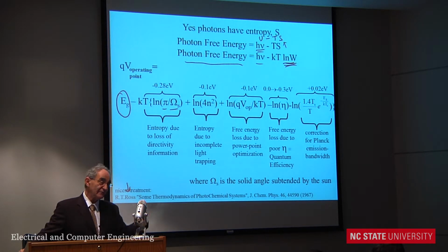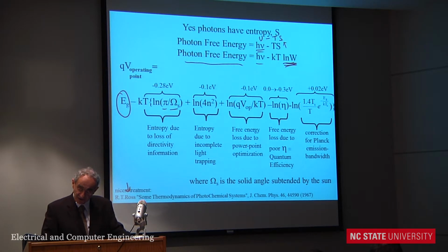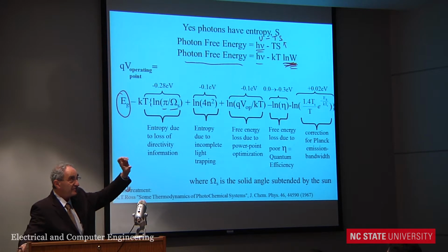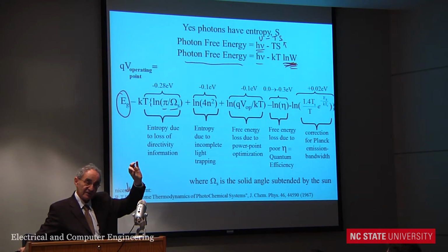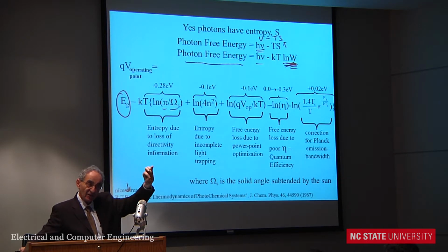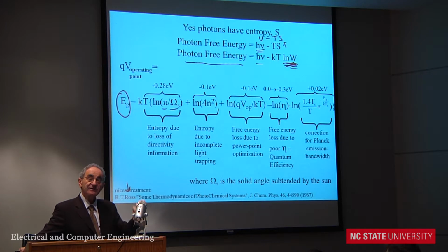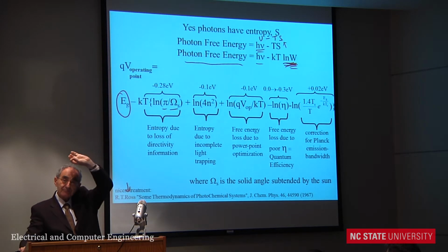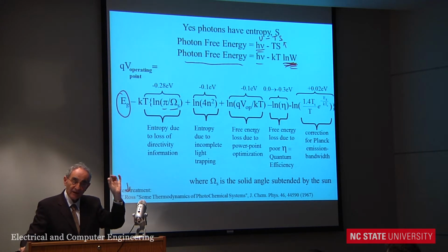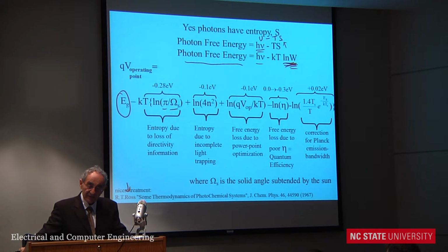Now, when you throw away information, that leads to entropy. That's the number of combinations. So I ask, how many different places in the sky can I put the sun? It's half a degree, which is about 1/100th of a radian. And then I square it to get the solid angle, so it's 1/10,000th. Then I put in a pi. There are actually 30,000 places in the sky where I could put the sun. Okay? And that means the number of combinations was 30,000.